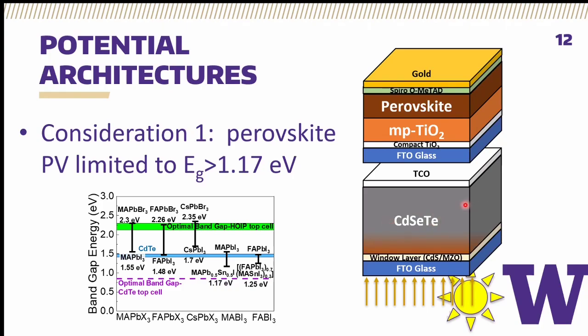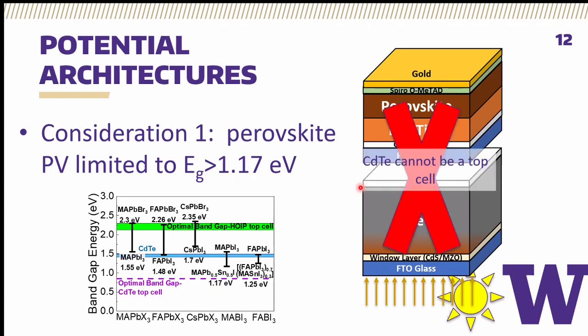That 1.42 eV is on the wider side of acceptable band gap ranges. So a really good CdTe tandem would have CdTe as the wider band gap material and a different narrow band gap device. Unfortunately, the range of known photovoltaic perovskites bottoms out at 1.17 eV, which is only 0.2 electron volts lower than the CdTe band gap. And every material that has band gaps between, let's say, 1.4 and 1.17, is tremendously unstable to the point that they're almost unusable, which is a further complication of this issue. Ideally, you'd want a really stable 0.8 to 0.95 eV band gap material as the pairing for CdTe. As it stands, perovskites can't achieve that, asterisk. We'll talk about that later. But CdTe cannot be the top cell.